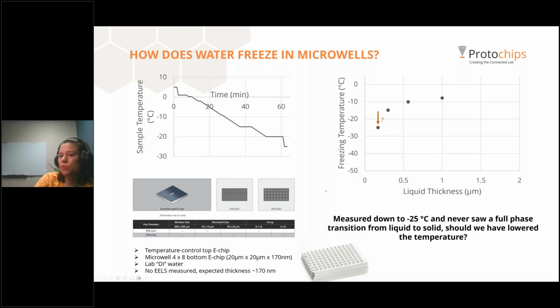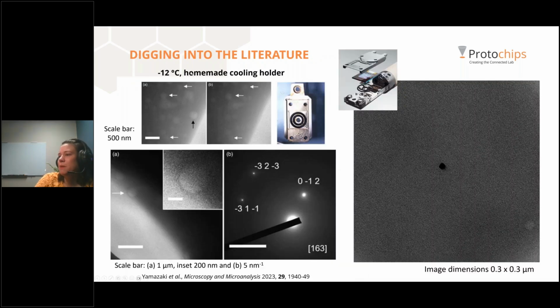When we looked at the literature, we found this paper from Hokkaido University where they made their own Peltier holder. And they went all the way down to -12 degrees. From what I can tell from the paper, they never saw a huge shift in the water to ice transition. But they did see these beam-induced bubbles forming. And when they did diffraction inside of these bubbles, they saw diffraction patterns. They saw crystals, indicating that they either had ice or a slurry of ice and liquid, or something of the like. So they actually do have ice in there, which was very interesting.